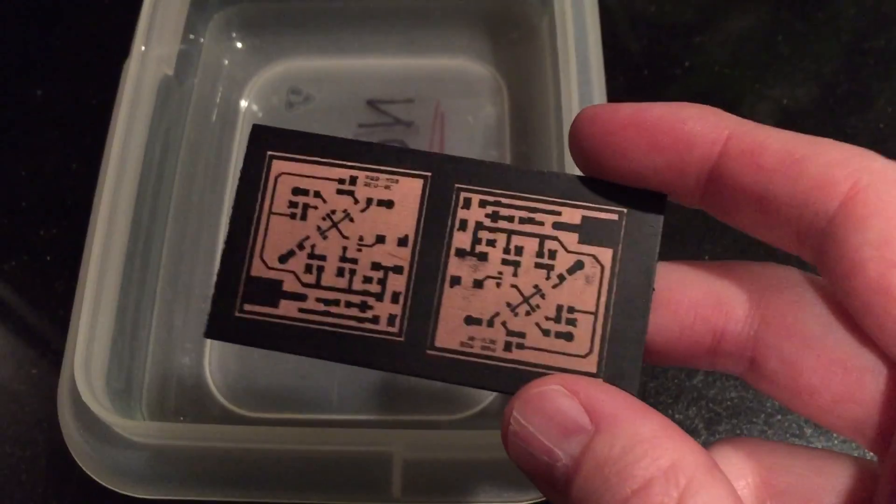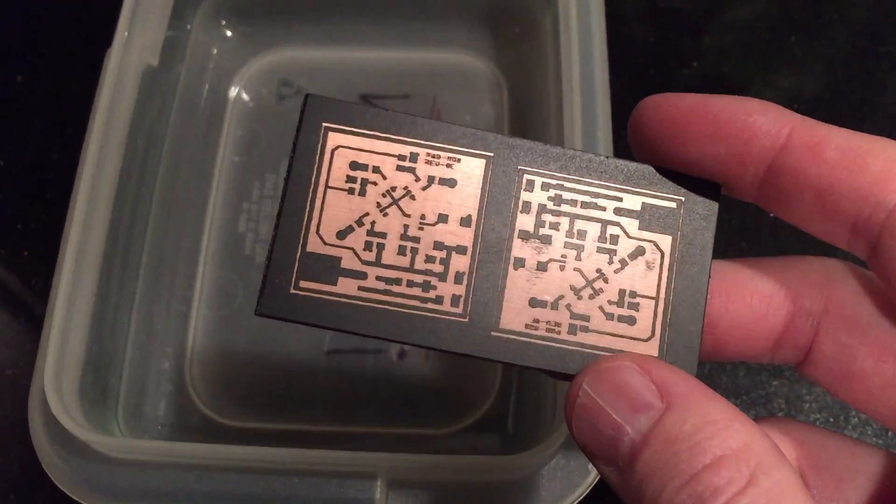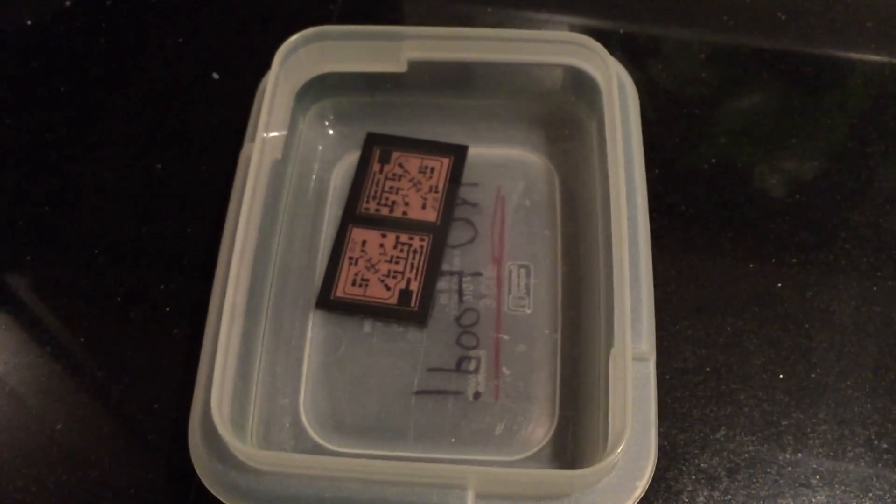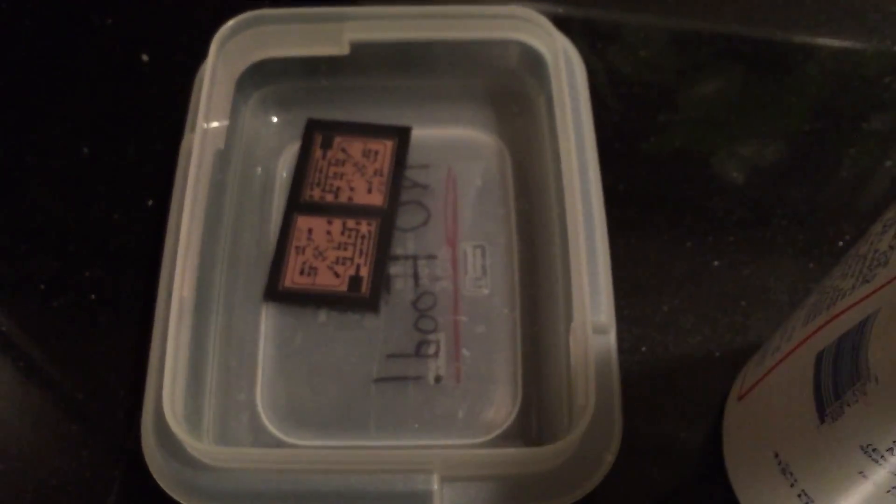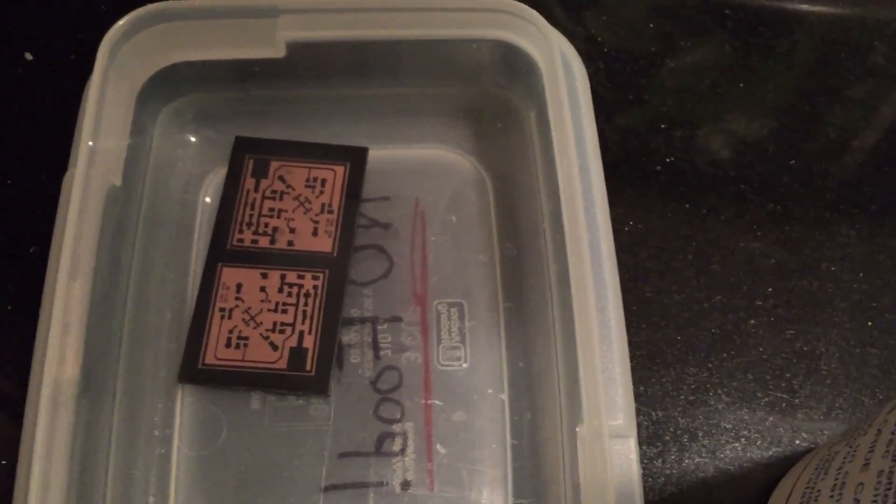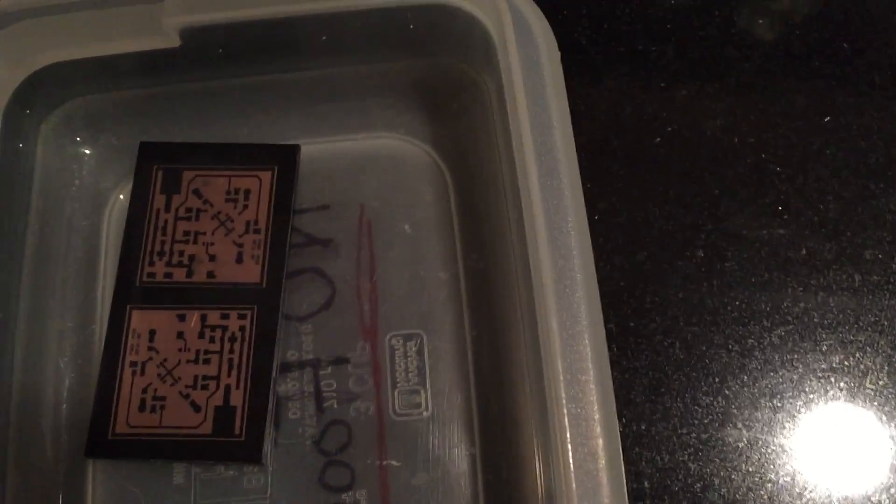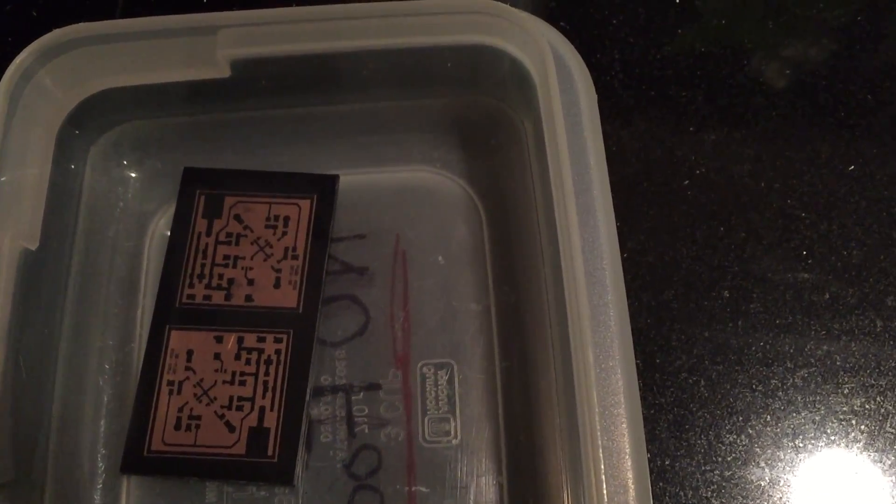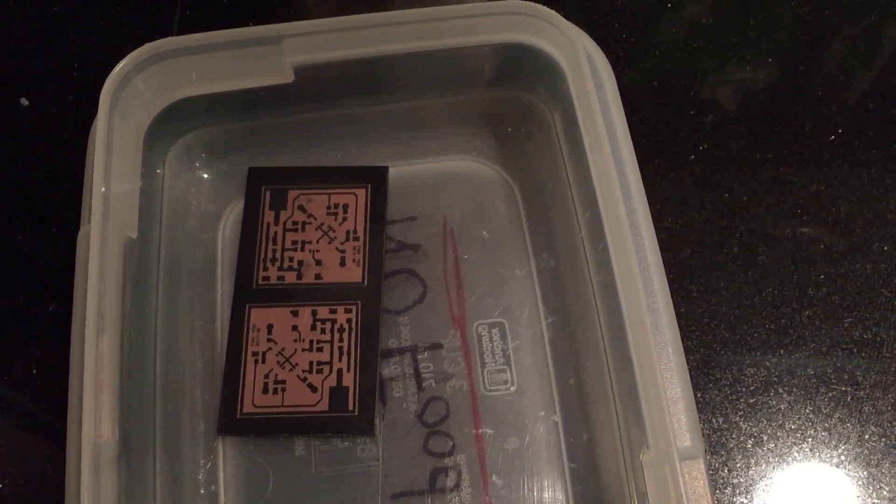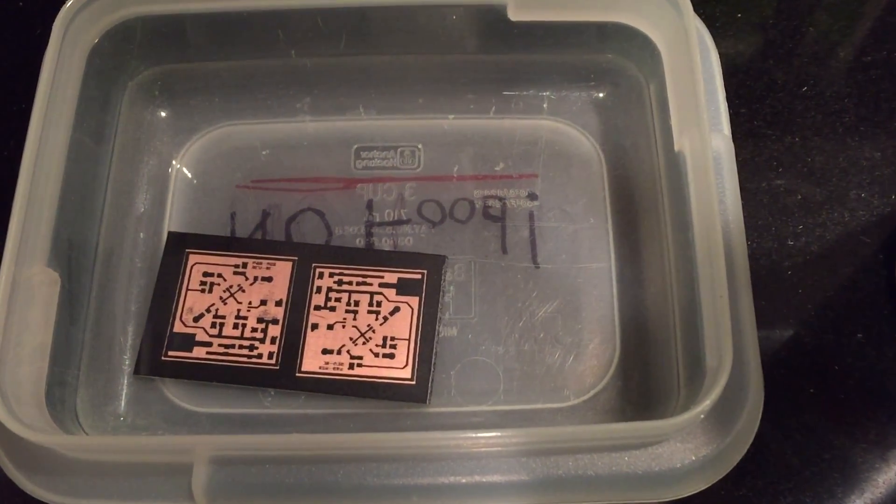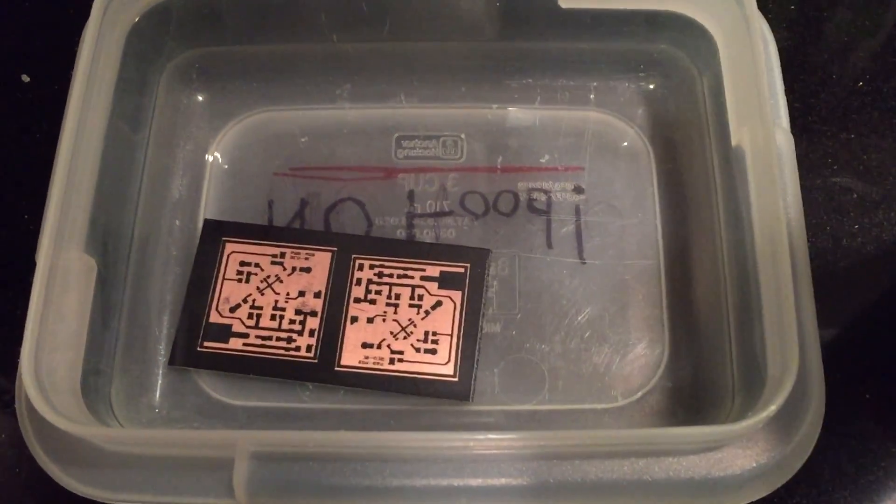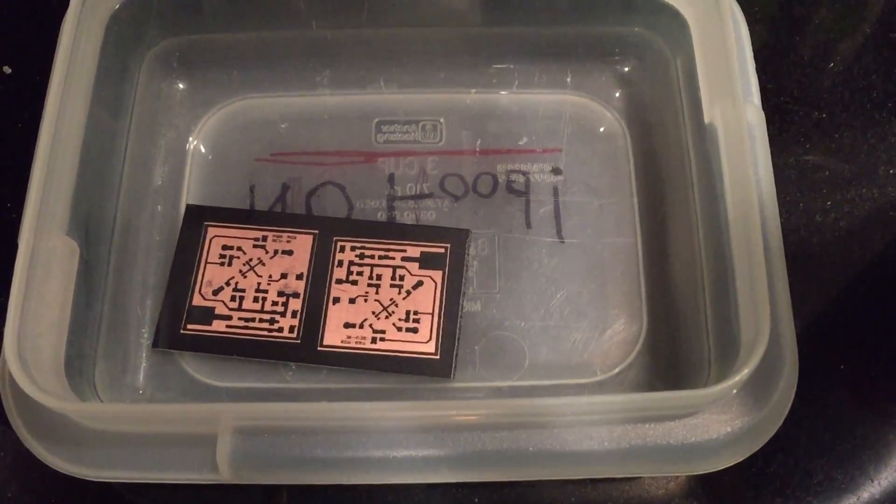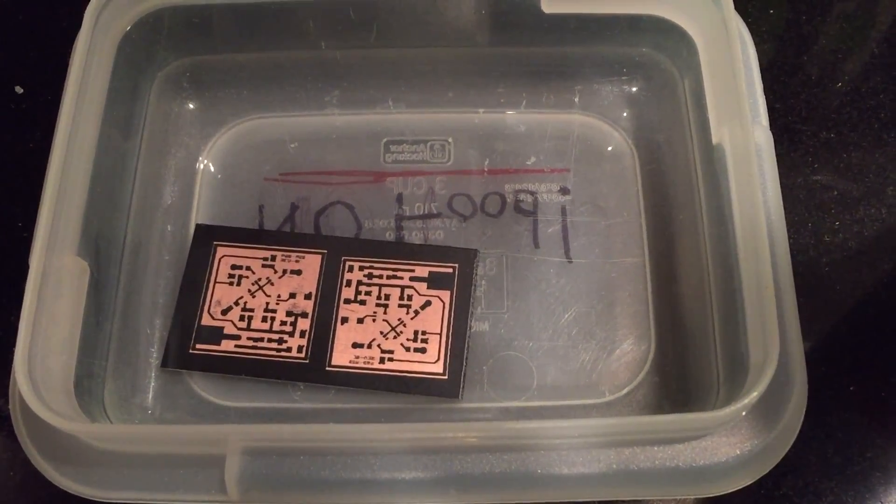It's all etched, or the resist is etched. I'm going to put it in my tray. I use ferric chloride because I'm just old school like that. I don't have an agitator or anything, I just sort of rock the tray back and forth. My chemical is just slightly warmer than room temperature. I know that causes the risk of under etching to go up, but I've had pretty decent luck with it in the past, so I'm going to try it with the laser cutter stuff and see what kind of detail I get out of it.